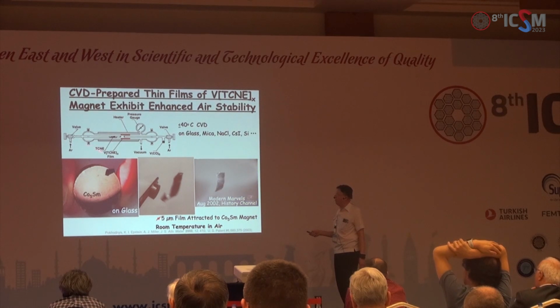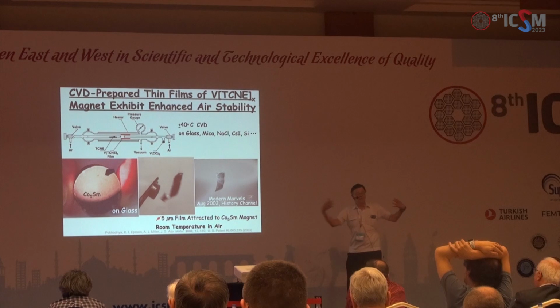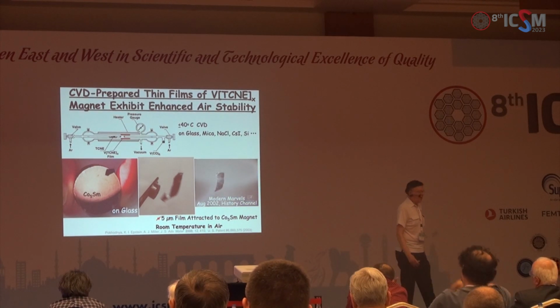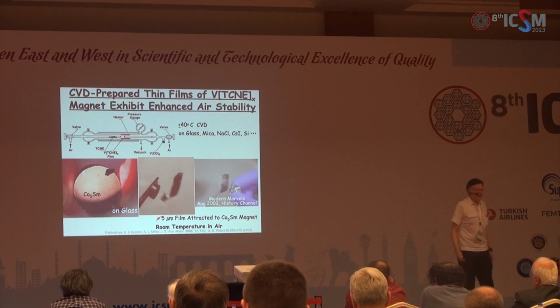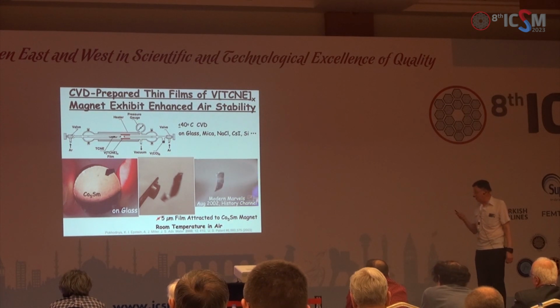Heating up a little bit more on the TCNE side, vapors at TCNE, they both mix. Anything in the middle gets coated with the vanadium TCNE magnetic material. You can see here there's less than a 5-micron coating of vanadium TCNE magnet on a piece